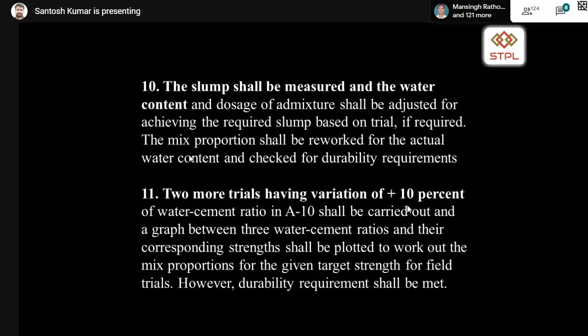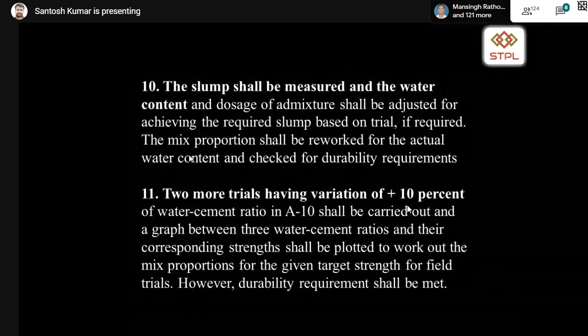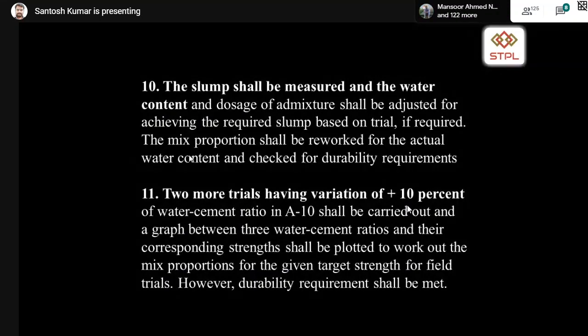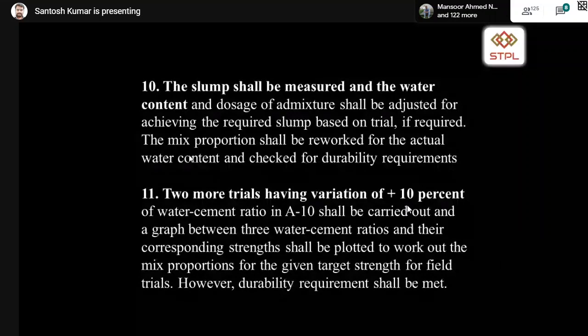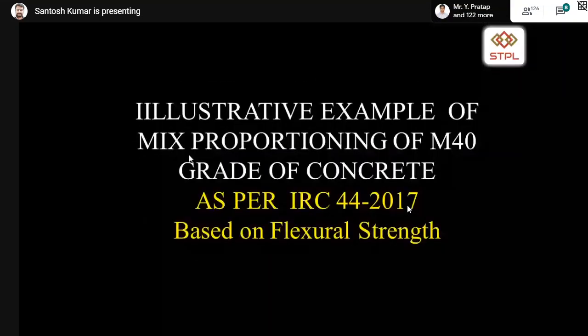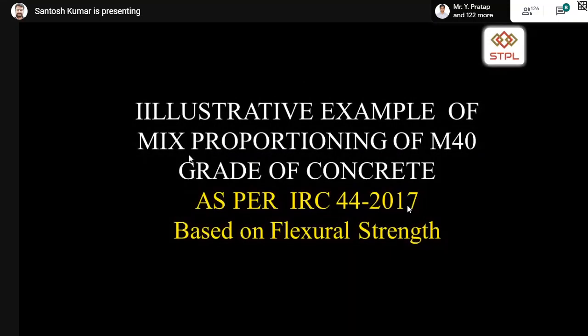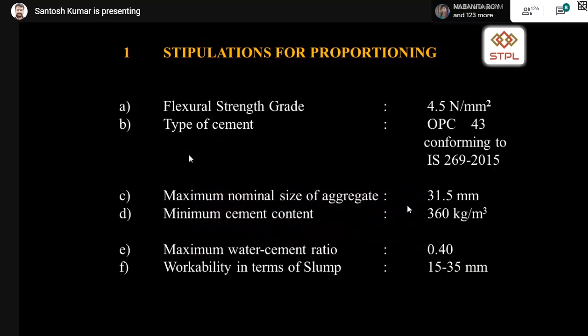Two more trials you have to conduct with a variation of 10% in the water cement ratio, and the strength shall be plotted. The optimum mix design has to be reported to the customer, or on the site you can use it. So another example I just wanted to show you for a normal M40 grade of concrete based on flexural strength. So the flexural strength grade is designed for 4.5 Newton per mm square.